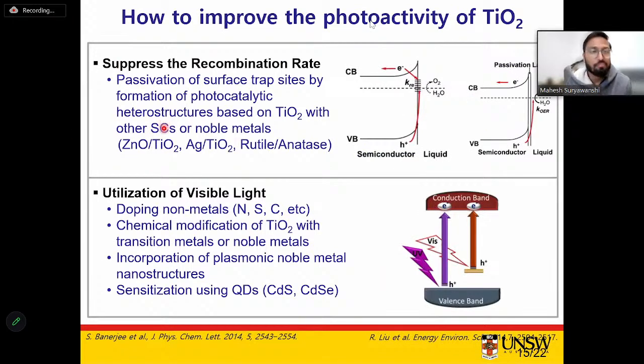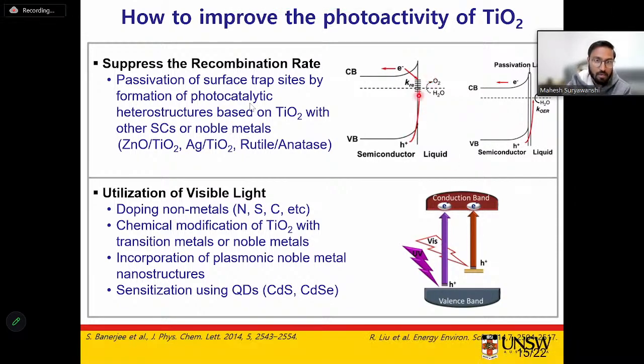Okay. So how to improve the photoactivity? As I said, this is what we have done so far, and this is what we are trying to do. How we can improve the performance of the TiO2, or simply photoactivity, is that when we grow TiO2, mostly using a hydrothermal method, there are some surface trap sites, or simply you can call them defect formations, on the surface of the TiO2, which actually act as electron recombination centers, or simply electron killing centers, that we need to passivate.